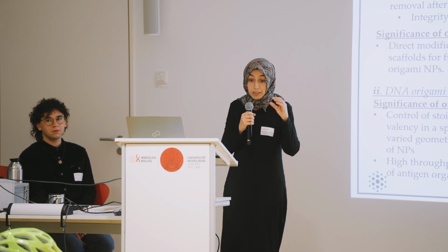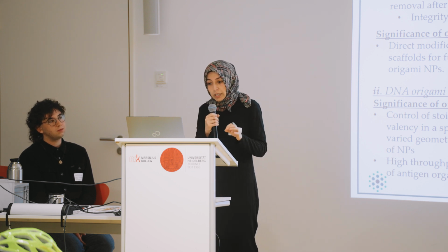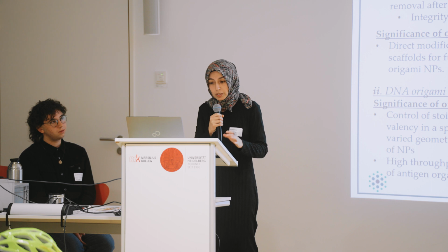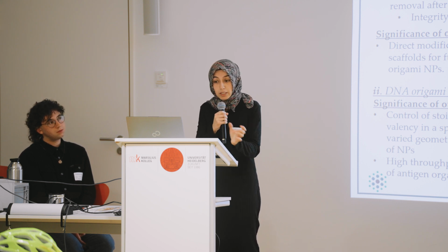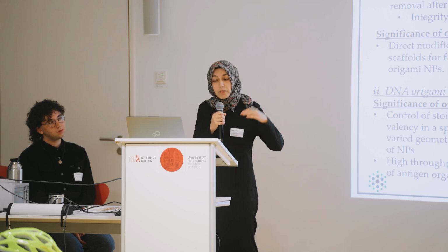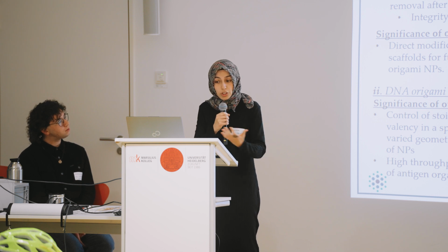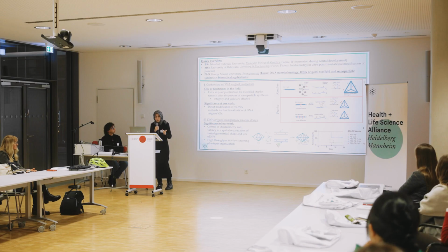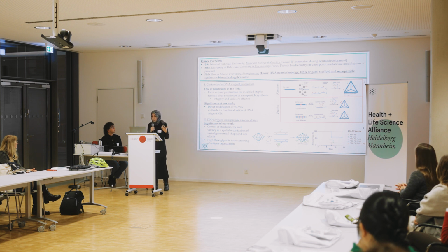We modify the synthetic DNA in three dimensions and attach different molecules at the same time for simultaneous presentation in the cell. Thereby we can control the stoichiometry and valency in spatial organization, by the advantage of the DNA itself, after folding the structure into any geometrical shape and size. Also, a benefit of this technique is that you can track your structure in vitro while controlling the organization or modification of the structure.